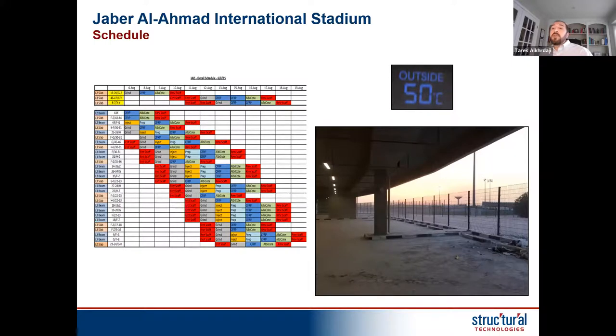But the challenge is when the temperature is too high and you mix the epoxy, because the temperature tries to cure it faster, it starts to become too thick within a short period of time. So rather than, let's say, a 2 hour window to work with the epoxy before it hardens, it drops to maybe 30 or 40 minutes, which makes it very hard to deal with. Because of that, the material in this case was kept in a cool place, some of it even in a big fridge, the epoxy. Then they mix it and install it, or do most of the installation at night. So these things need to be considered. It's not as much of a concern in Canada because the temperature is never that high and we don't have issues there.